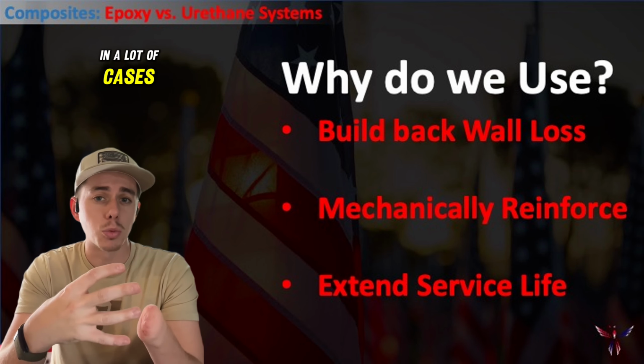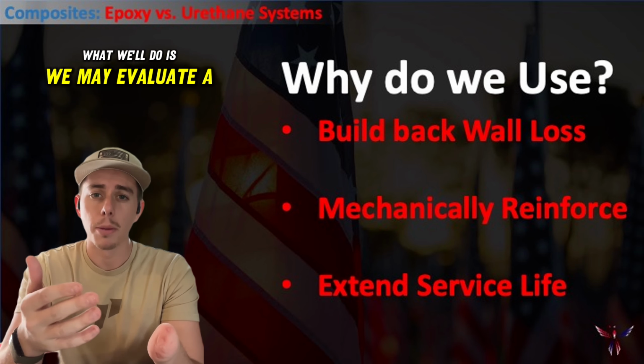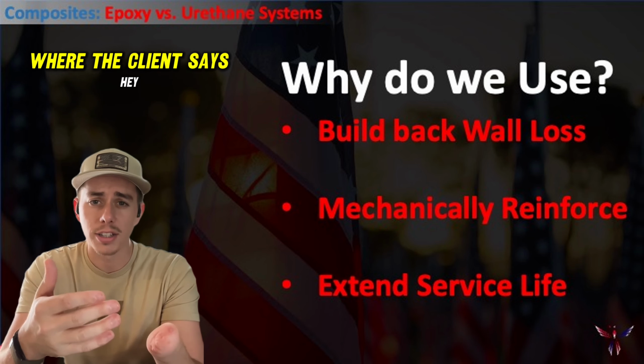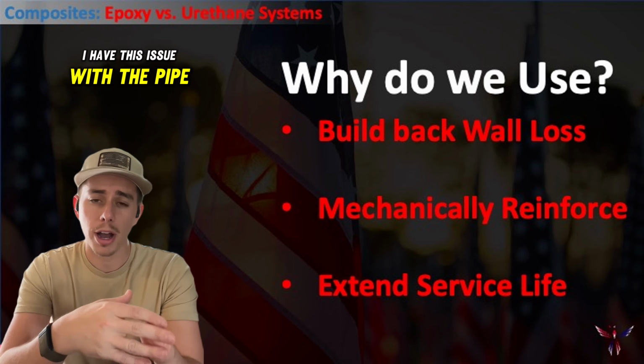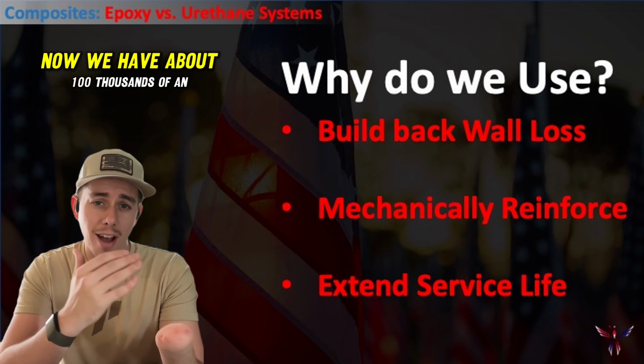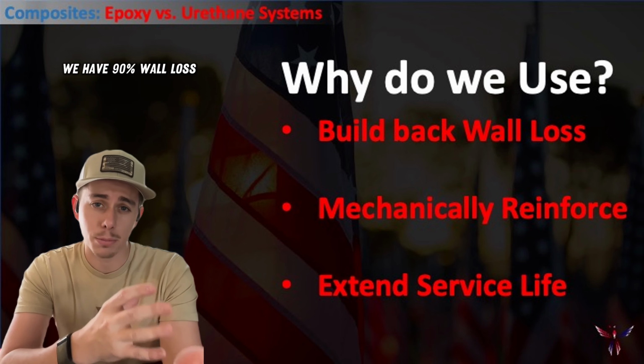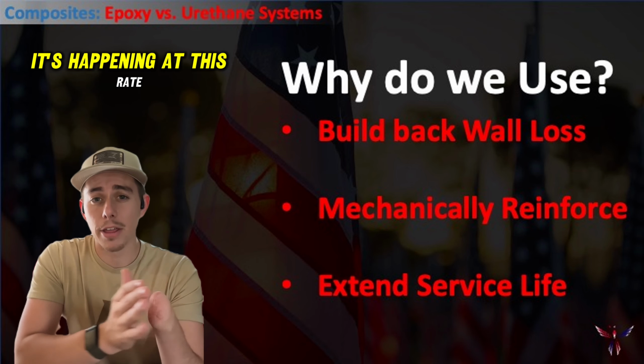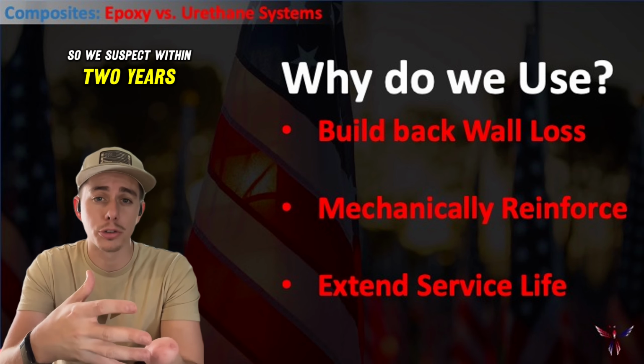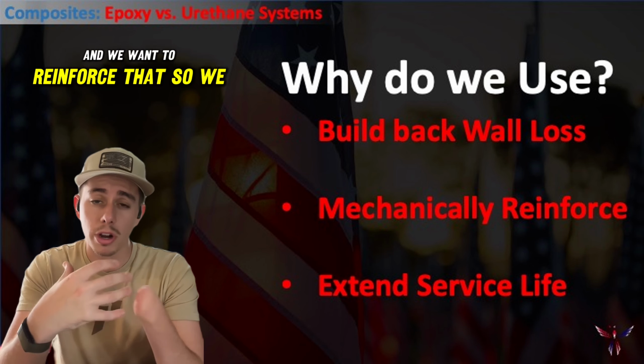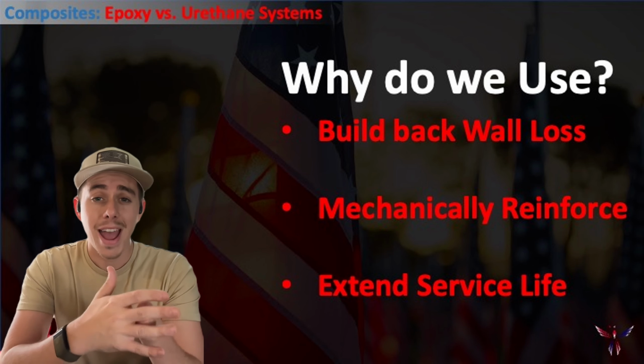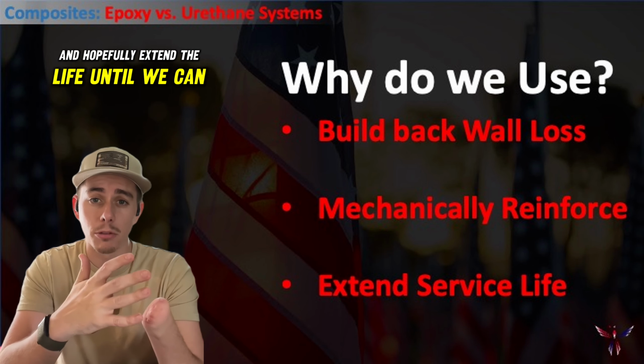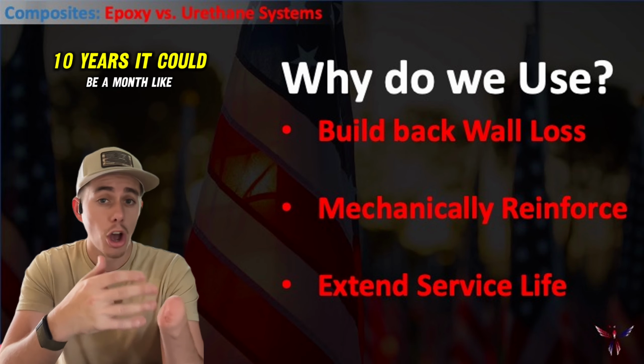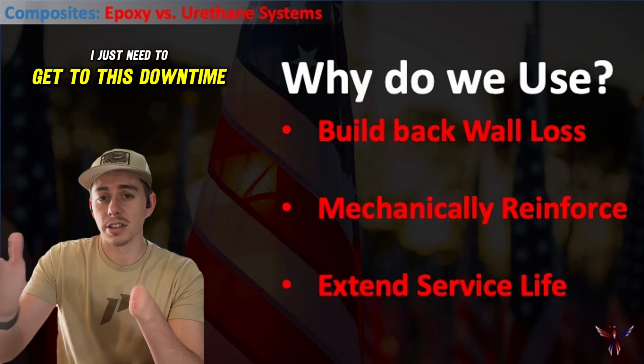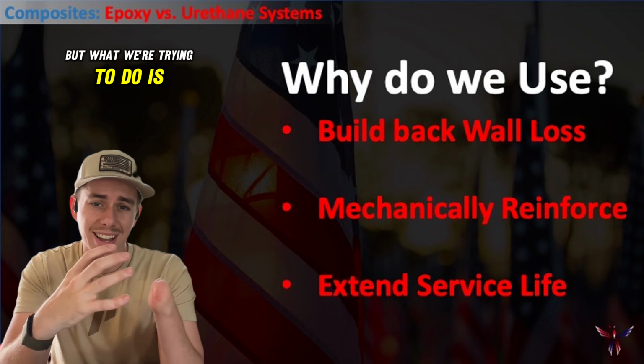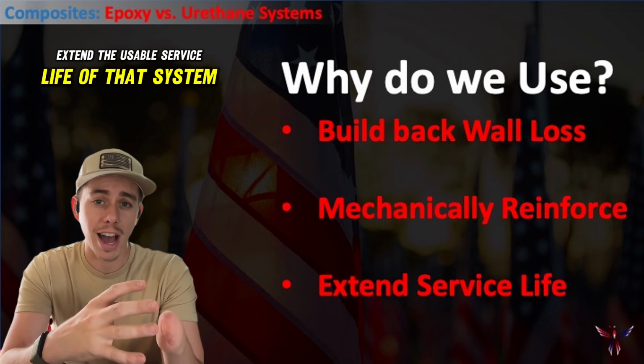In a lot of cases, what we'll do is we may evaluate a piping system where the client says, hey, I have this issue with the pipe. We had an inch of wall, now we have about 100 thousandths of an inch, so we have 90% wall loss. It's happening at this rate, so we suspect within 2 years we're going to have an issue, and we want to reinforce that so we can keep operating and hopefully extend the life until we can replace it in, say, 5 years, 10 years. It could be a month, like, hey, I just need to get to this downtime. But what we're trying to do is extend the usable service life of that system.